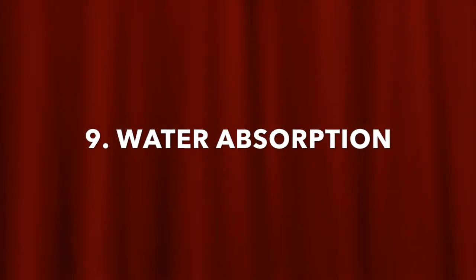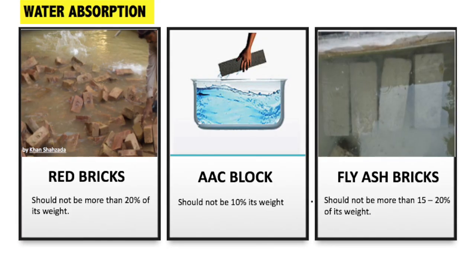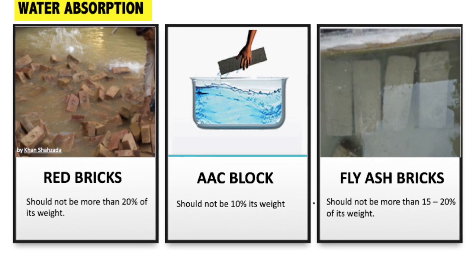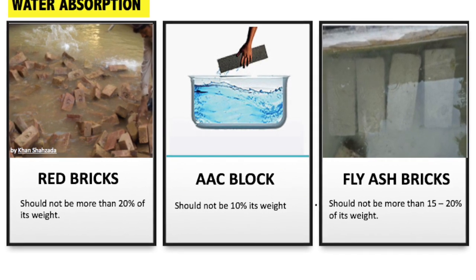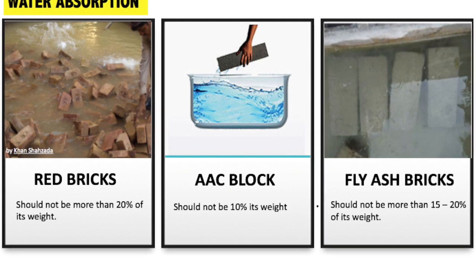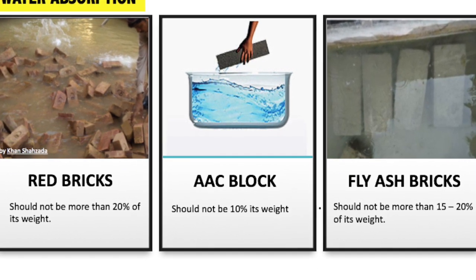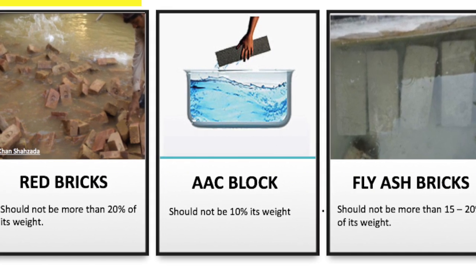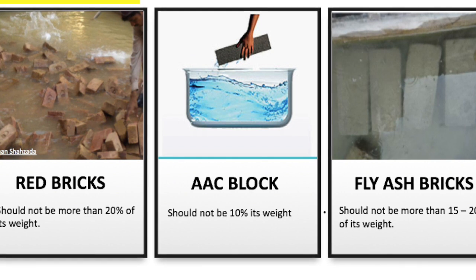Point 9: Water Absorption. Water absorption in red bricks should not be more than 20% of its weight. Water absorption of AAC block should not be more than 10% of its weight. Water absorption of fly ash bricks should not be more than 15-20% of its weight.